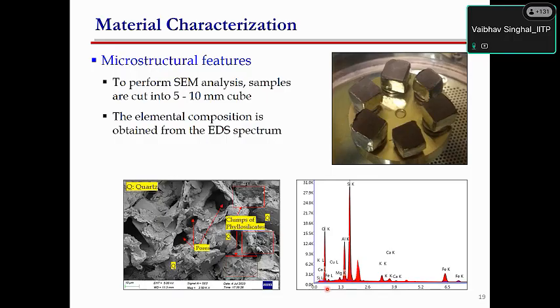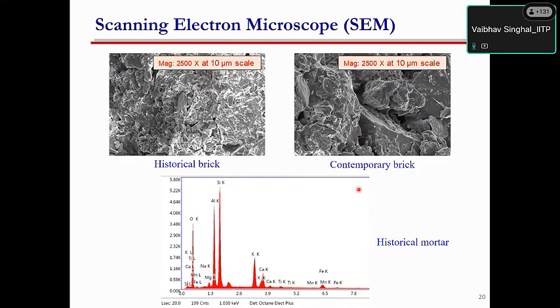And then one can also do detailed characterization. One can know about the microstructural features of materials, such as for the bricks. This is the SEM test for the brick. Bricks are coated with some metallic material; gold or silver is more popularly used so that you can get a good reflective surface. And using this SEM, one can know about the composition, what various minerals have been used for the manufacturing of these bricks. You can also know about what the firing temperature could have been during that time. It was interesting. We have seen that even during that time, the bricks were properly made in furnaces, in brick kilns, and the firing temperature for those bricks was also close to 900 to 1000 degrees centigrade.